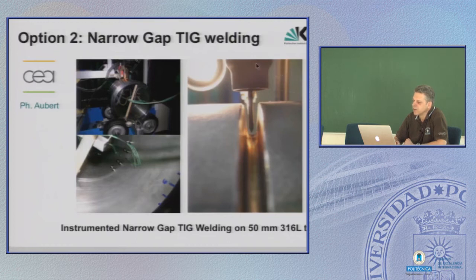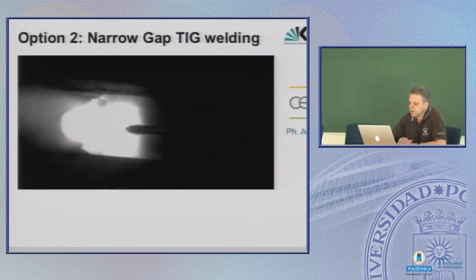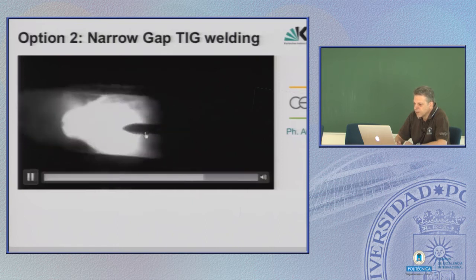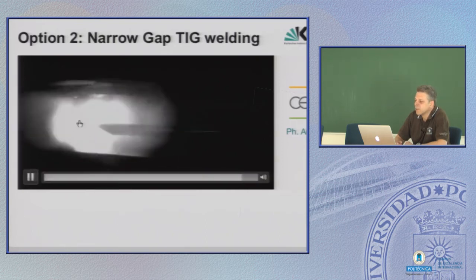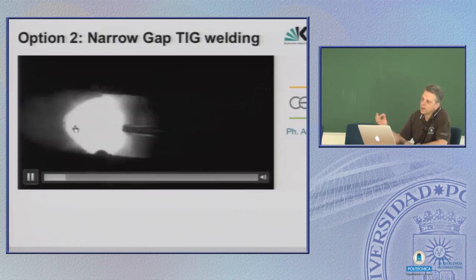At CEA in France they developed the possibility to do this narrow gap welding with tungsten inert gas. This is the electrode. This is a gap, in that case, between a tube of austenitic steel, which is used in fission technology, and here it works. Here you see a movie of such a weld process. You can see here the electrode, the arc, and somewhere here at the bottom is the filler wire.